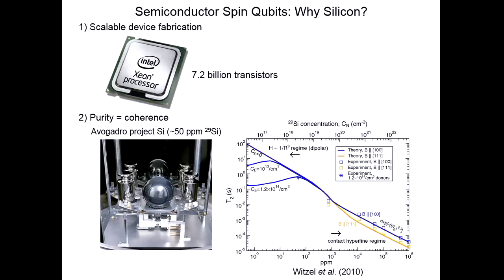The main reason for switching from III-Vs to silicon is just coherence. And this is a theoretical prediction from Sankar Das Sarma's group. It shows the coherence time, I don't know if you can read that in the back, as a function of isotopic enrichment of silicon. Right? So silicon has 3 naturally occurring isotopes, silicon-28, silicon-29, and silicon-30. And silicon-29 is about 5% in natural abundance. That's the only spin-carrying naturally abundant isotope in silicon. Okay? So if you start at natural silicon, you have a T2 that's maybe 10 microseconds.